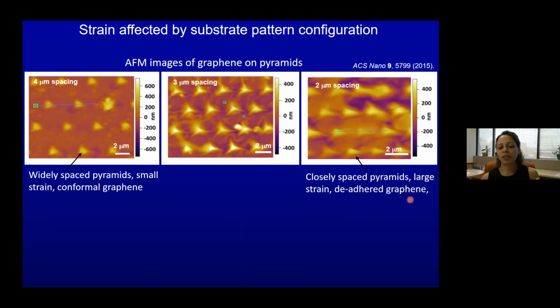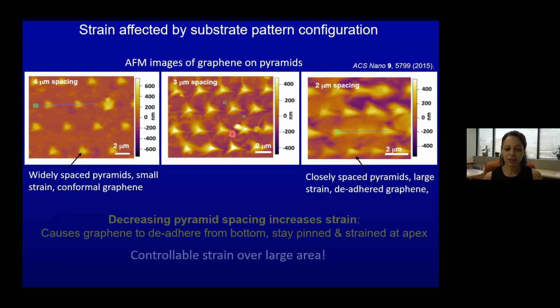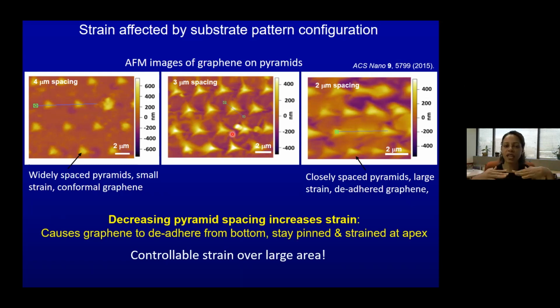And then as you make these pyramids as close together as we could, which is a couple microns, suddenly you see these large regions of bright spots, which tells you the graphene de-adheres from the surface. So we've reached a point where the adhesion energy is smaller than the strain, and rather than stay strained, the graphene just pops up. And so what this tells us is that we can control the strain in graphene just by controlling the configuration of features that it sticks to, okay? So this is nice because it tells us that indeed, if we do create this sort of nano-patterned substrate, we can achieve strain over a large area of graphene, which is what we are aiming for.